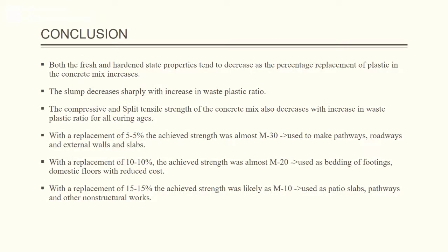Conclusion. The present study observes that both the fresh and the hardened state properties tend to decrease as the percentage replacement of plastic in the concrete mix increases. The slump decreases sharply with increase in waste plastic ratio. These types of mixes can be utilized in situations which require low degree workability.